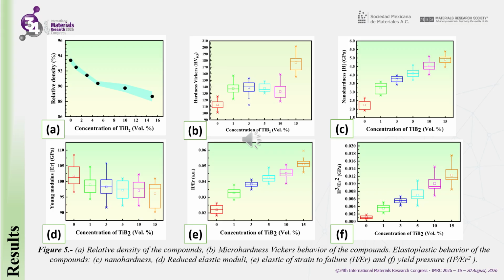The results obtained from the nano-indentation test indicate a nanohardness behavior similar to that of the Vickers microhardness test, with a gradual increase in nanohardness with respect to the percentage of titanium diboride. It is evident that the reduced elastic modulus decreases as the titanium diboride concentration increases. Concurrently, the ratio of nanohardness to reduced elastic modulus represents an elastic strain to failure, and the ratio of nanohardness cubed to reduced elastic modulus squared, representing yield pressure, increased with the rising titanium diboride concentration, indicating an enhanced resistance to adhesive wear.